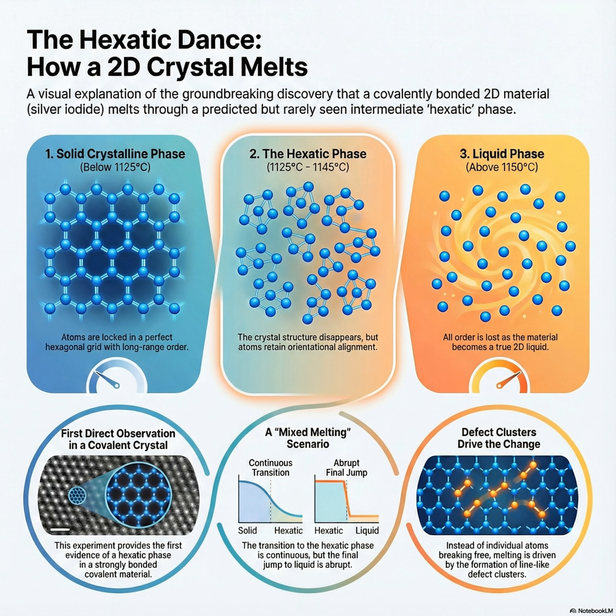Okay, key takeaway 1. Melting in atomically thin materials follows rules that are fundamentally different from 3D melting. This research confirms that the stable, long-range ordered hexatic phase exists, and it's achievable even in strong, covalently bonded materials. It's not just for soft systems anymore. And key takeaway 2. For this specific high-strength material, the final step into the liquid state is abrupt. It's a first-order transition, which validates the mixed melting scenario. And we know why. The defects cluster together to form grain boundaries, physically separating the two coexisting phases.